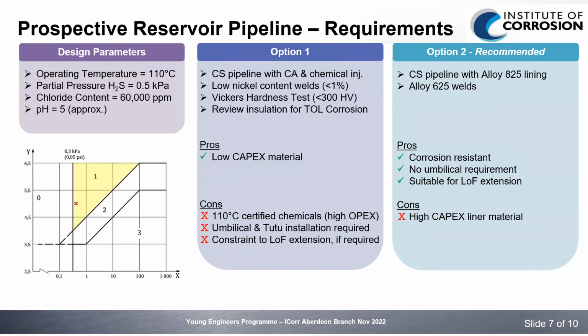What that means for our material selection is that our first option is an ISO 15156 certified grade carbon steel pipeline with sufficient corrosion allowance and chemical injection as well. For welding consumables for this material, we would recommend low nickel content, less than 1%, so we don't get localized hardness, which would then be subject to sulfide stress cracking. We would then do a Vickers hardness test to ensure the material has a hardness within the limits specified for region 1. Another consideration that would require further review is whether we would need to insulate this as well to protect against top of line corrosion due to the carbon steel material.